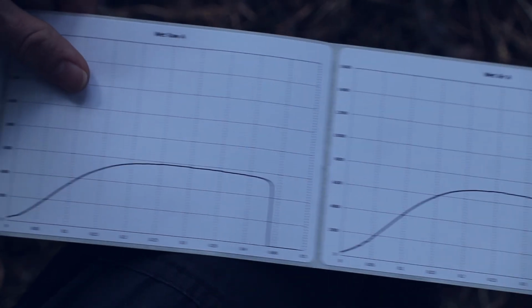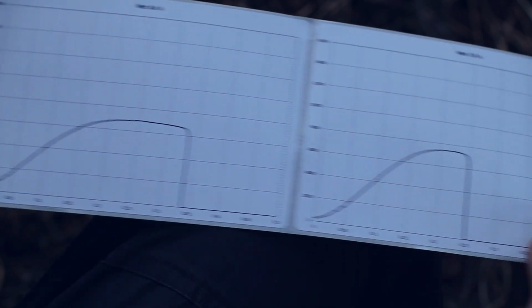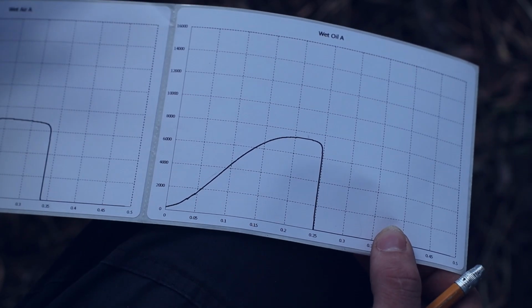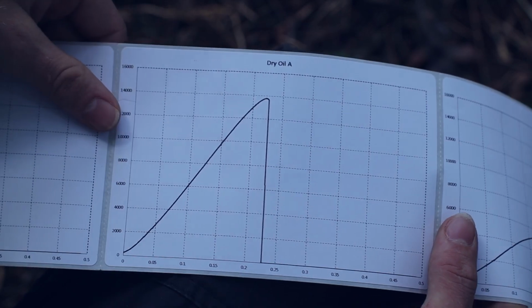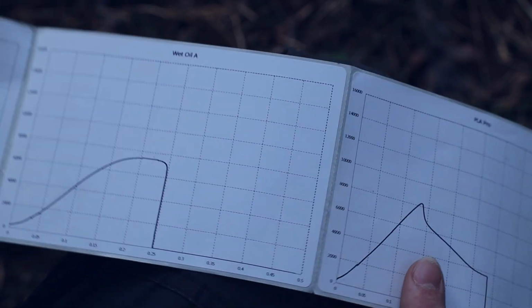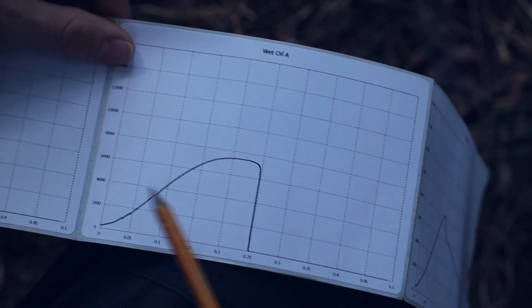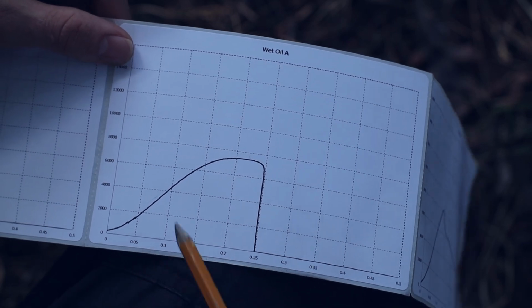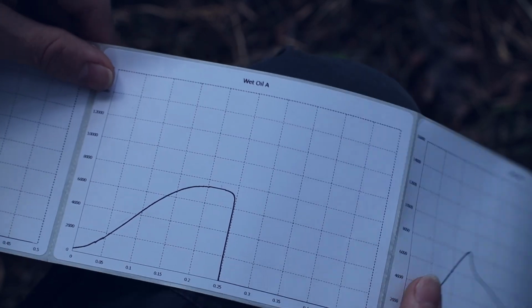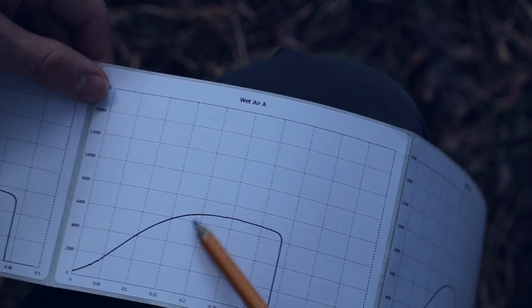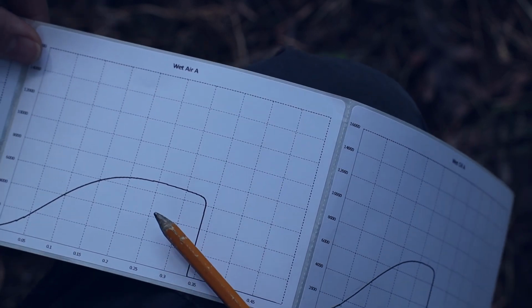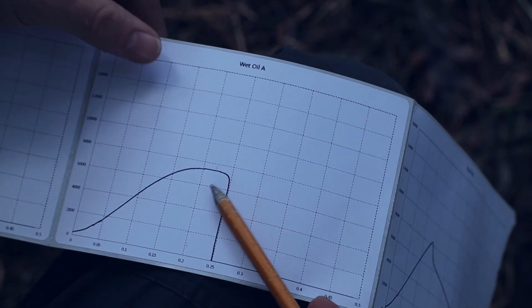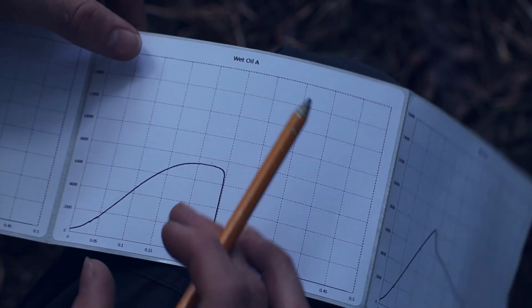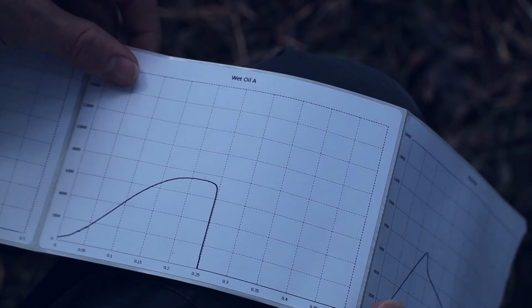The trend here can be clearly seen that our sample is getting stiffer and stronger and more like our dry sample. That leads me to believe just plain annealing increases the strength of the material by crystallizing the nylon, but by itself it doesn't do that much good. And if you combine the plain annealing with the oil, the oil is preventing moisture absorption and getting you closer to the dry nylon, which has actually pretty good properties.